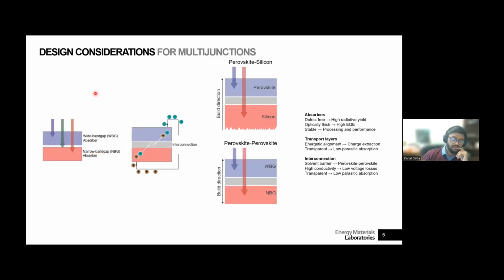So in terms of what you need to think of with respect to how to design a tandem in each of these platforms. This was the schematic that I showed, but actually if you need to make a monolithic device, you need to introduce something called an interconnection layer, right? And that is where the charges, so the electrons or the holes, depending on the polarity, from the narrow bandgap cell and the opposite charge from the wide bandgap cell recombine, and that maintains charge neutrality. And that gives you a good device, right?